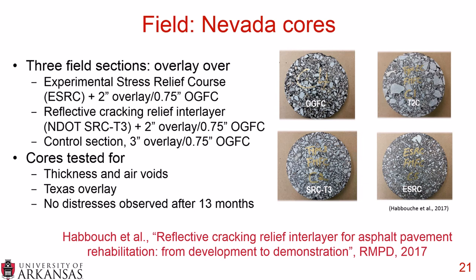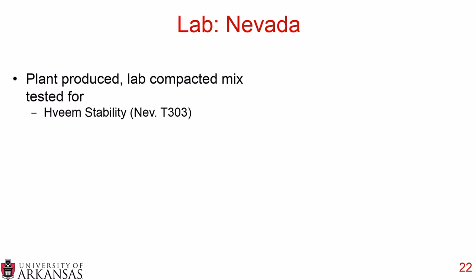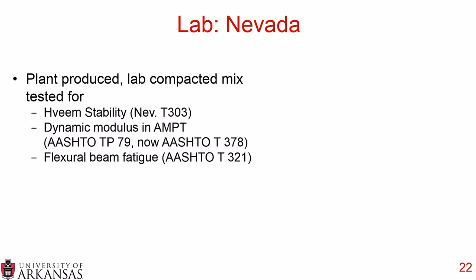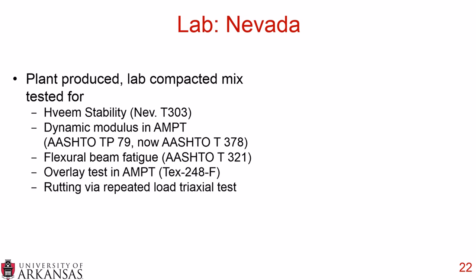So the first half of this study looked at the cores and examined the field sections, and the other half went to the lab. They used plant-produced lab compacted mix. They tested for Hveem stability according to Nevada T303. They looked at dynamic modulus in the AMPT, and when they wrote this paper it was AASHTO TP79, but now it's AASHTO T378. They tested flexural beam fatigue, AASHTO T321. They tested the overlay test in the AMPT following Texas 248F, and they also quantified rutting via a repeated load triaxial test.